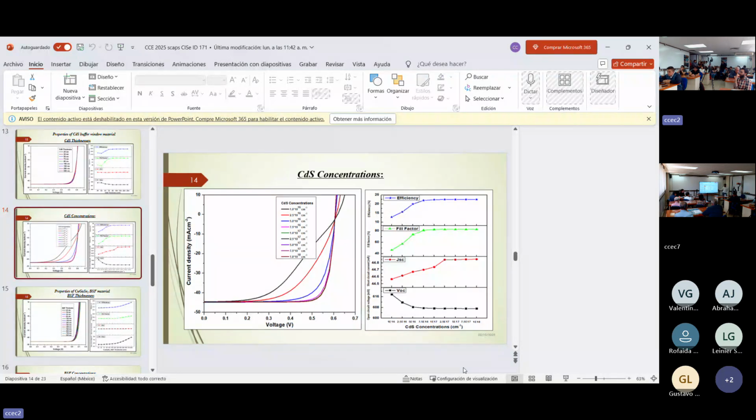For example, for this material, I use the chemical deposition method. There I have used urea and cadmium acetate, also aluminum acetate, as reagents. What I initially did in my practical experience was vary the cadmium acetate using the same concentration of urea. By increasing the cadmium acetate precursor, from my experience, it can increase the cadmium concentration.